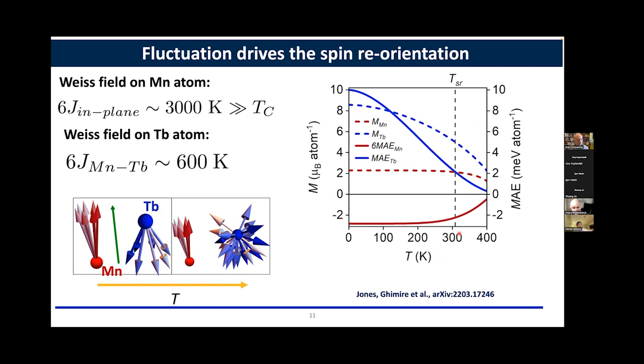Now, interestingly, what we see is that at high temperature, the magnetic anisotropy energy of manganese is larger than that of the terbium. This is negative. That's why it favors in-plane orientation. This one is positive. It favors out-of-plane orientation. And at 310 Kelvin, they become equal. And below 310 Kelvin, the anisotropy of terbium wins over the manganese. That's why the moment starts rotating from in-plane to out-of-plane. And that's one of the things that we realized. So this is about the spin reorientation induced by, or mediated by, the fluctuation.